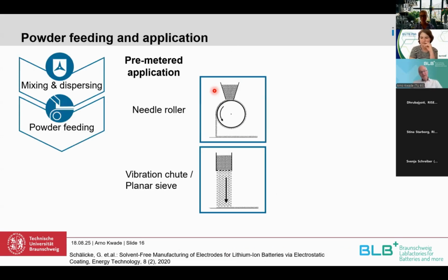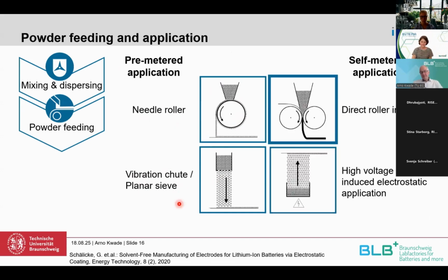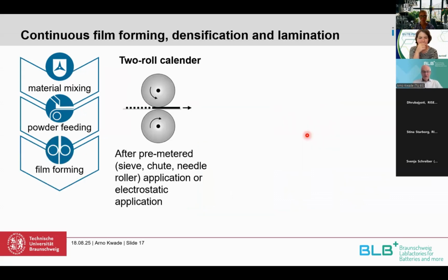Now coming to the dosing. If you look in the literature and also the patents which are available, you see that we already have some pre-metered applications, like is typical for wet processing. For example, you can choose a needle roller, a vibration chute, or a planar sieve. But what is most common are still self-metered applications using a direct roller infeed with a calendering. Also, there are some electrostatic applications which are patented. But by far the most common one is using a direct roller infeed in a calendering machine.